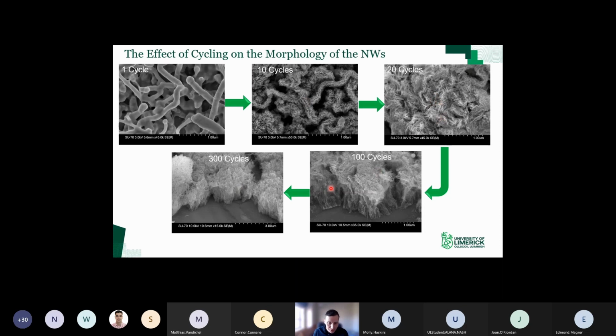And then after 100 and 300, you can see the nanowire morphology is gone, and it's been replaced by this porous interconnected network of active material. Importantly, between 100 and 300 cycles, you don't see any more deformation. So what's formed after 100 cycles looks almost identical to what you have after 300 cycles, which is very good. And it's the reason why our material has such good capacity retention, because once this structure has formed, it doesn't deform any further. Once you get down to a ligament diameter of about 5 nanometers, it doesn't deform any further.